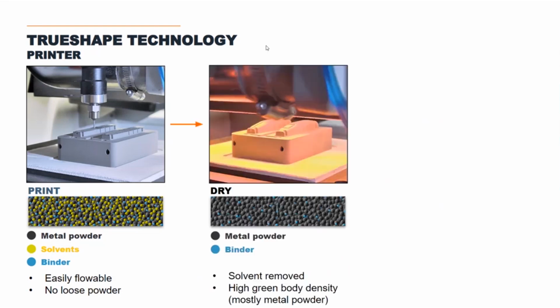After every layer is printed, we go through and dry the layer. We only need that solvent to make the material viscous enough that it can flow. So we come by and we dry the layer with heat and with air to remove that solvent out, just leaving behind metal powder and binder. At this point, it's firm. It's firmed up almost to about the same as a dense foam.